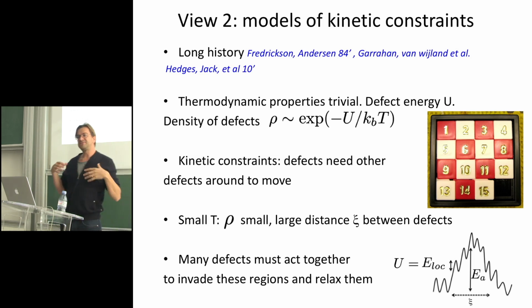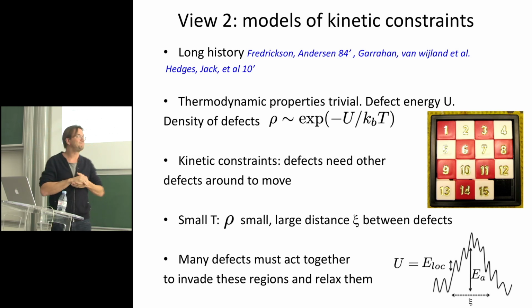Well, in those models, typically these defects have some energy. And so if you lower the energy U, so if you lower the temperature, you have less and less of those black defects. So you have big regions without defects. You have a length scale that grows, just the distance between defects. And in the most interesting model, the black squares cannot move alone. They need other black squares to move. And so you have those big regions as you lower the temperature where you don't have any black squares, and they need to be invaded by a bunch of black squares together to relax the system.